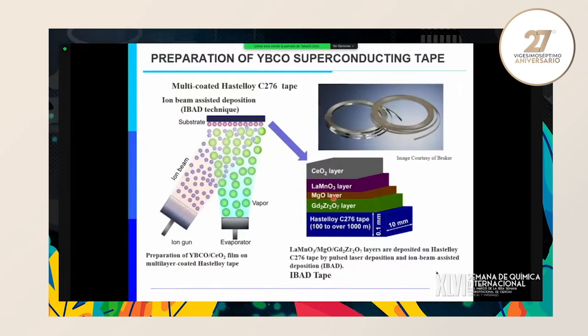Superconductor film is much more critical. Superconductor tape is now commercialized, like this one. So superconductor YBCO is prepared on metal tapes, multi-layer coated tape. Superconduction takes place along the C-plane, so we have to prepare C-axis-oriented YBCO epitaxial film on IBAD tape. Metal tape is, of course, polycrystalline, and therefore we need many layers. That's the reason this becomes a multi-layer of gadolinium zirconate, magnesium oxide, lanthanum manganite, and ceria.